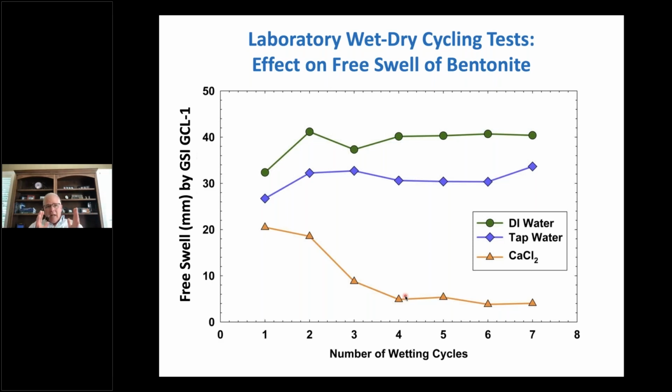And if it cracks and it can't swell back up when it hydrates again, it will remain cracked and very permeable. And that's exactly what happened at this field site. Exactly what happened. You saw the cracks early on in the photograph. Those cracks did not swell shut upon rehydration.